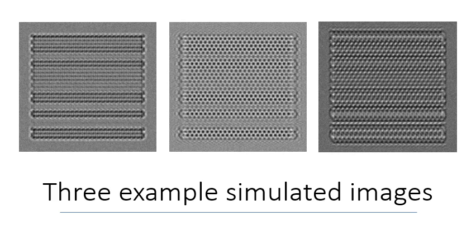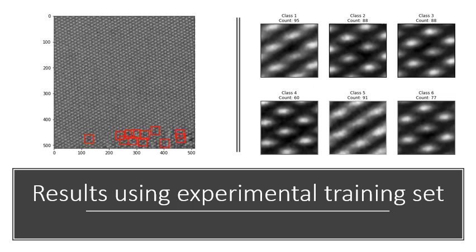Using autoslice algorithms, we generated 1,000 training images with the areas of defects already known to us. And this is the result after training the neural network using experimental images. It finds all the defective regions automatically and categorizes them without any human input. All these classes are decided by the neural network. However, notice it is not perfect because we used only a single frame manipulated 1,000 different ways. A better result can be obtained using simulated images, but that is still a work in progress.